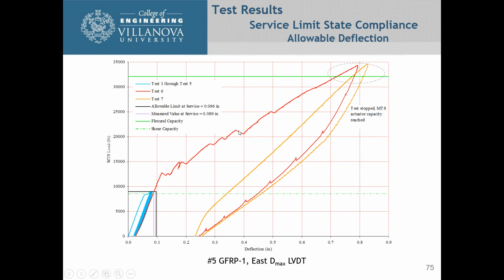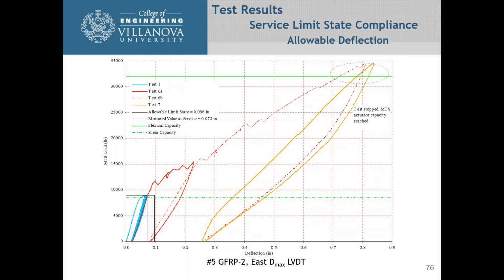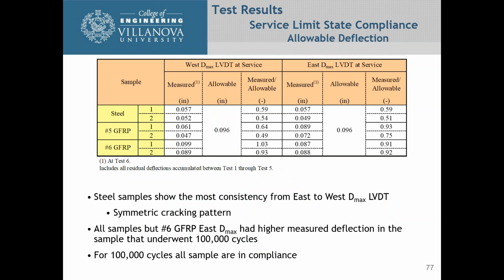Again, you can see as we were trying to take this thing up to failure, we got it past the point that we calculated out what the flexural capacity was, but still we're not able to break the beam. Here is another number 5 GFRP bar, and there again you can see that the allowable is 0.096 and the maximum measured value was 0.072 at service.